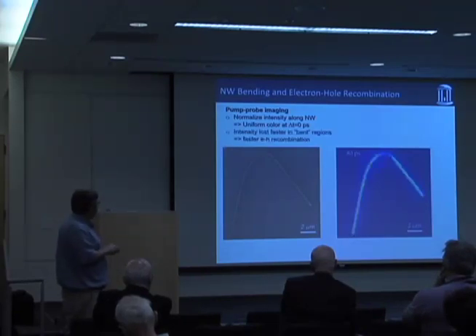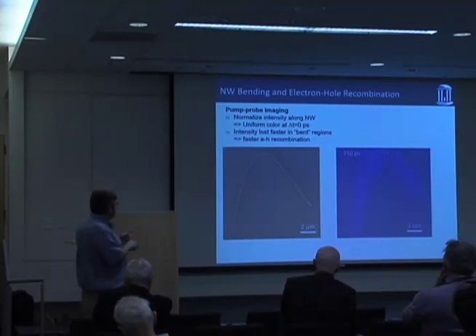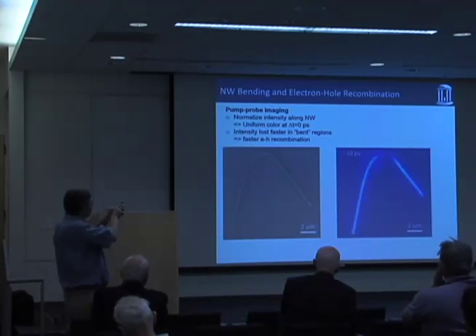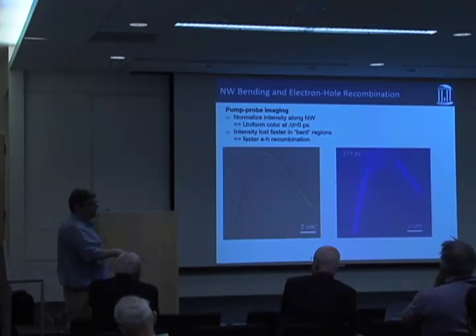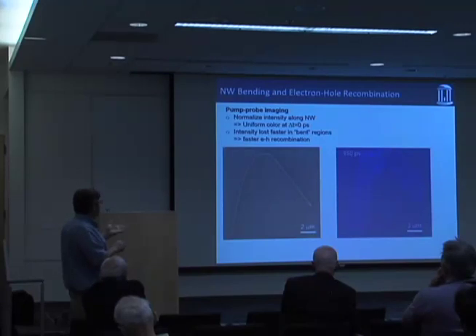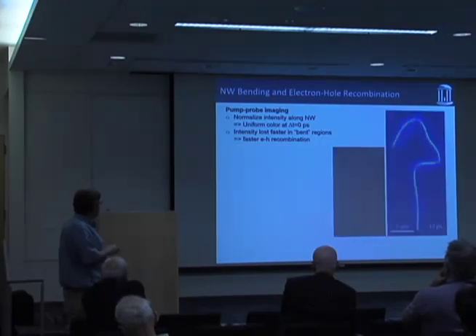And now if you look at it, and it'll cycle around in a second, you see that sure enough, this bent region goes away faster. And if you stare at it long enough, what you'll actually see is that the bent region eats away at the image as it goes along. So not only are the bent regions faster, but there's a correlation between the lifetime and the curvature of the wire. And this is in many wires.